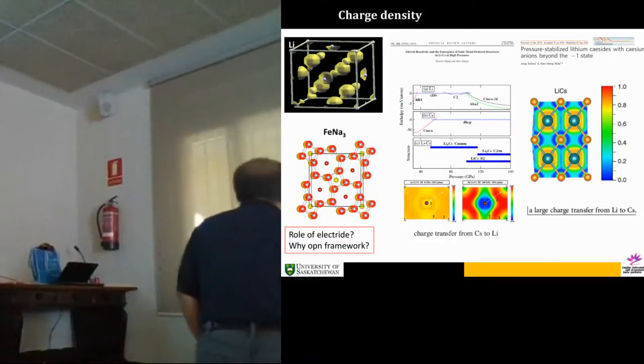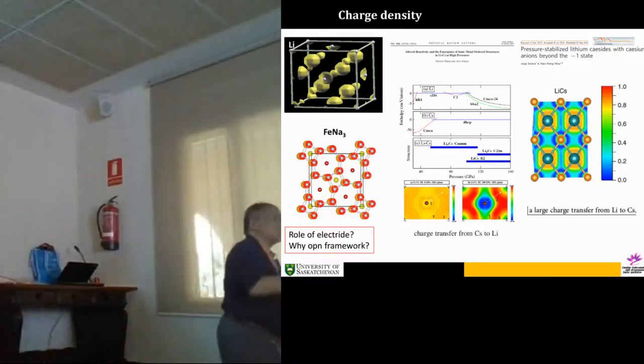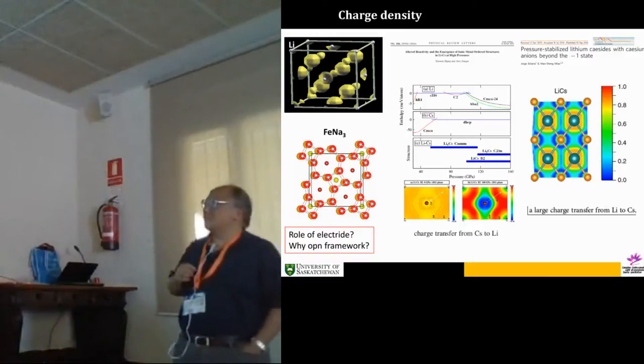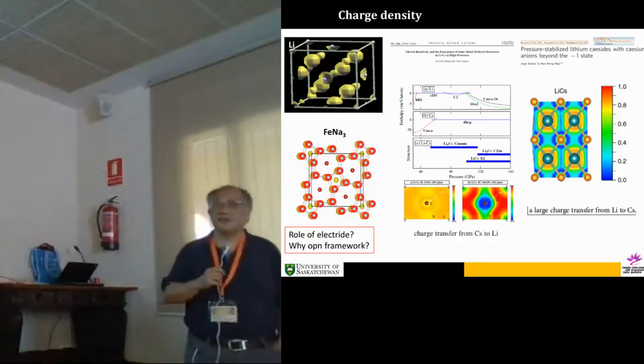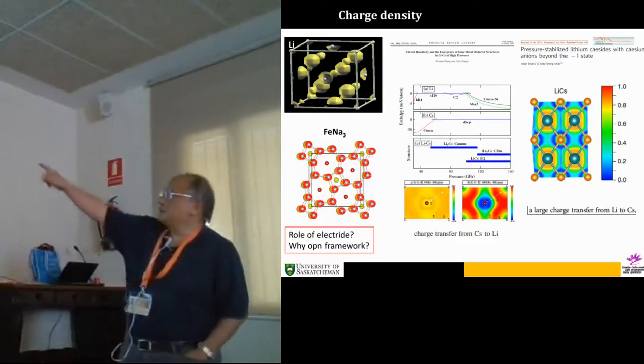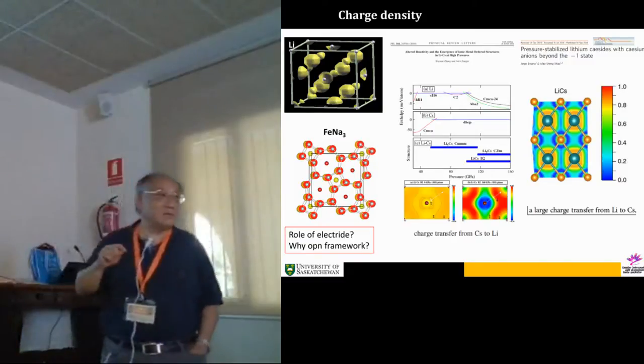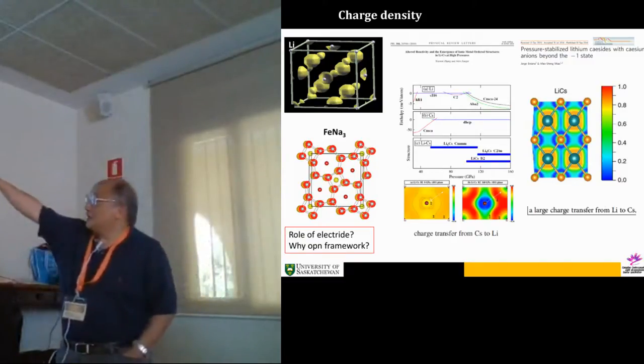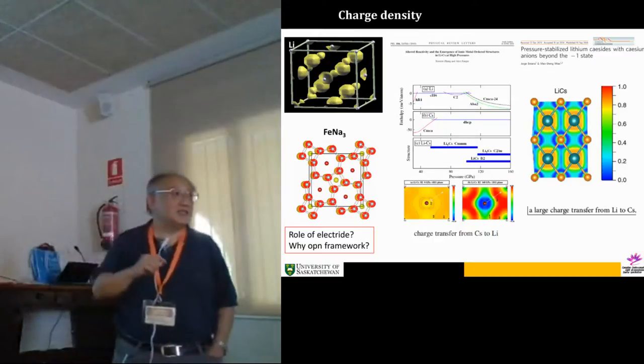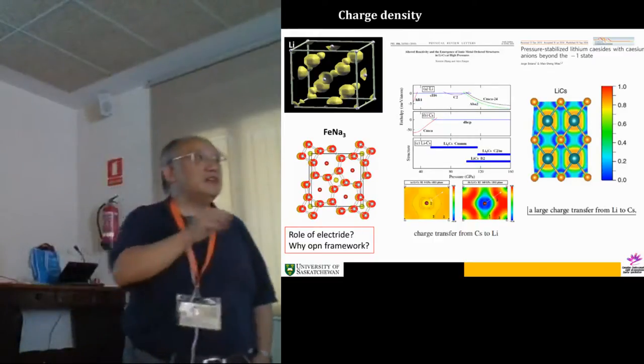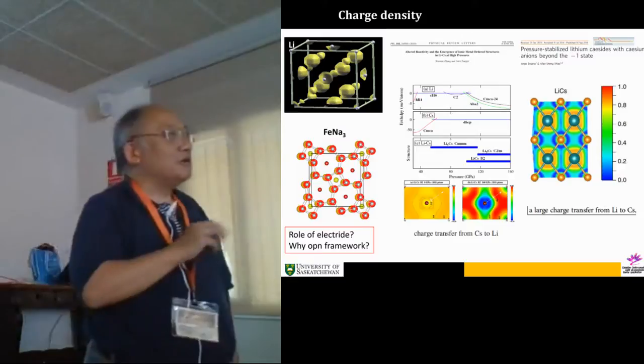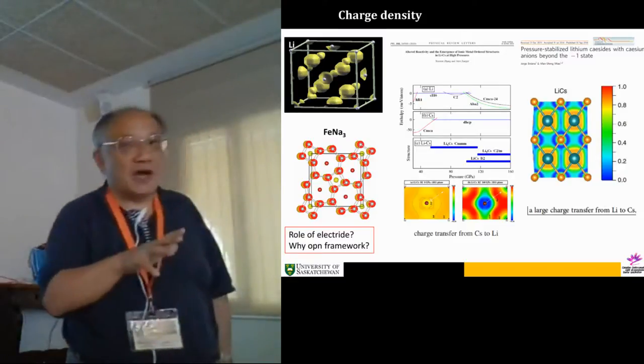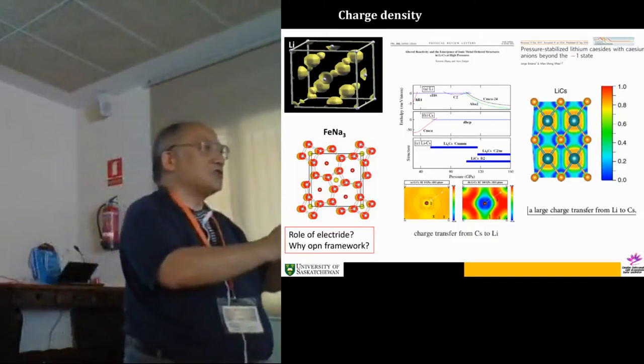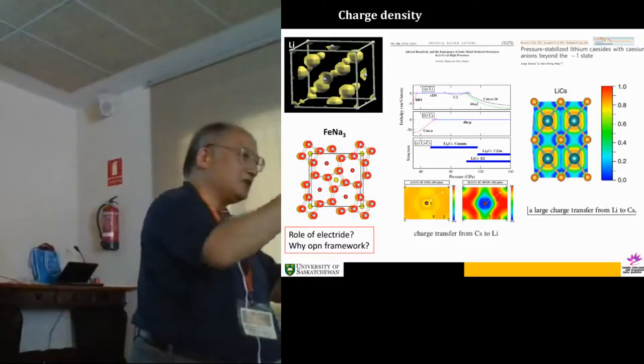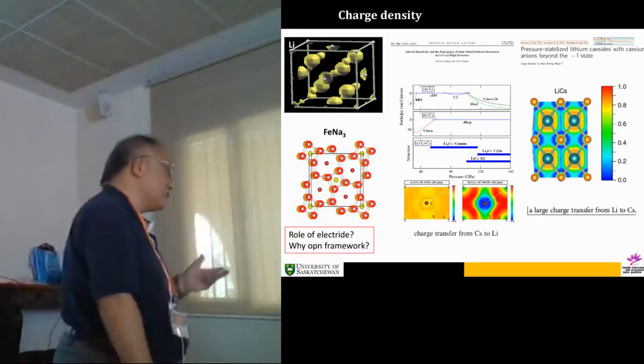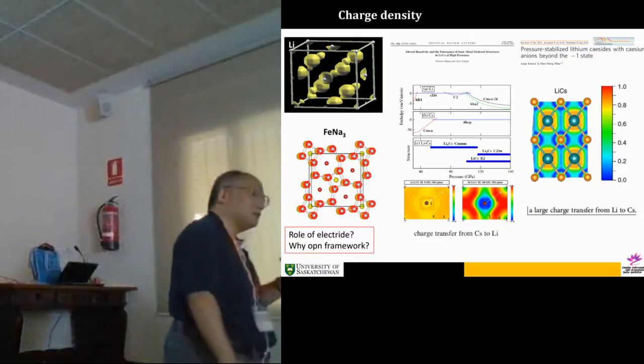So I go back to the charge density, my love of structures. This is a calculated structure of lithium at very high pressure, 450 GPa. You can see the white balls are the lithium atoms. And they are electrides, that means electrons localized in the interstitial sites. It raises two questions, actually. One question is what are they doing there, and why do they form this particular structure with the electrons in the interstitial site. The second thing is more important from an experimental point of view.